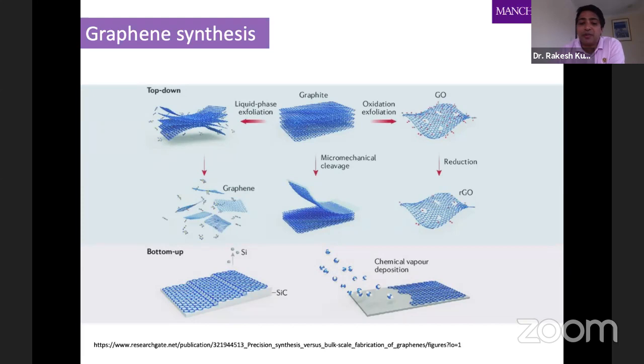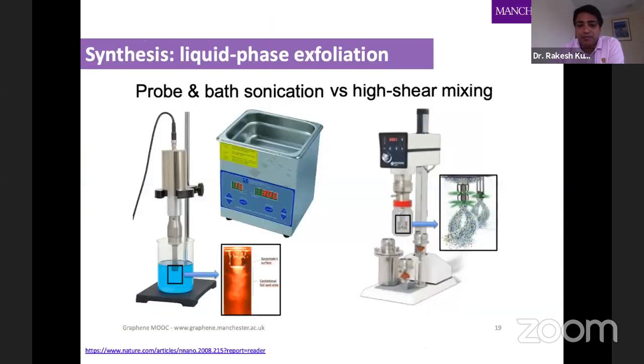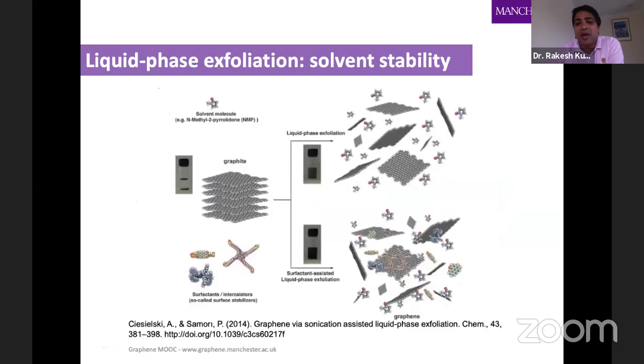This is called chemical vapor deposition, where you can deposit graphene on a metal surface or on a silicon carbide substrate. So for the liquid phase, we generally use these instruments in order to break down graphite into graphene sheets. We may have two methods that I was telling about: liquid phase and the oxidation process. By liquid phase, you sonicate this at a high sonication energy and try to isolate these sheets from the graphite with some solvents. Even water can be used, but for surfactant-based liquid phase exfoliation, you use some kind of